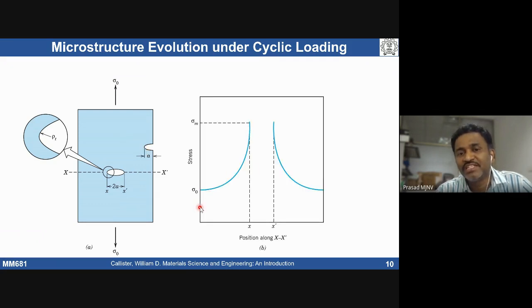Though I'm applying sigma naught, assume there is a center crack inside. Around this crack, the stress is going to be very high. Near the crack tip it can be infinity if it is a very sharp tip; depending on the sharpness of the tip, the stress magnitude is going to change. Though I'm applying a sigma naught just below the yield stress, if a crack is already present or has been initiated during deformation, we do see so much plastic deformation can take place around the crack tip. So the stress is going to be much higher at the crack tip, depending on sharpness.